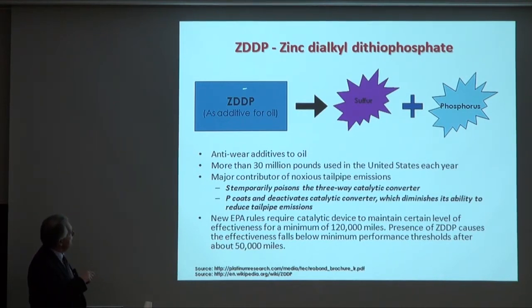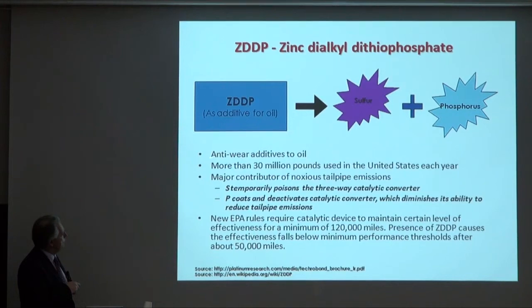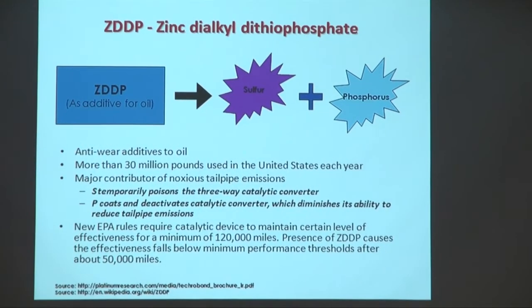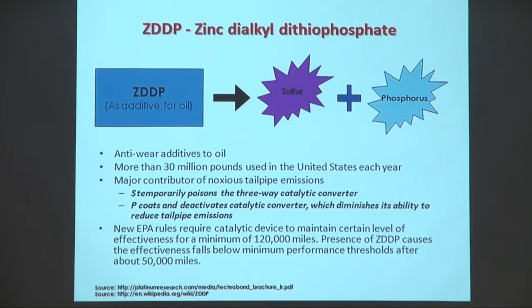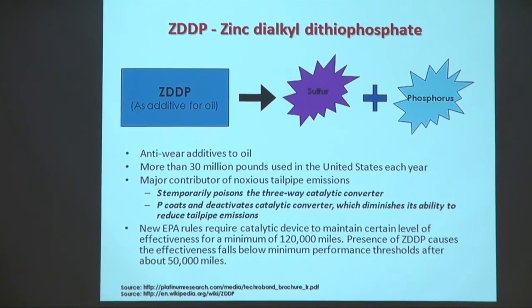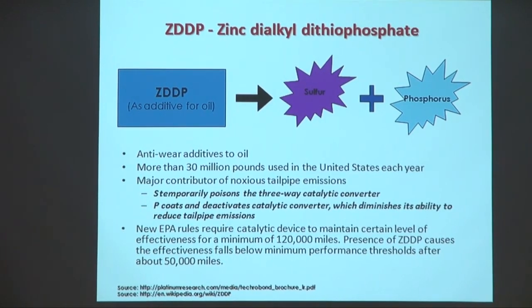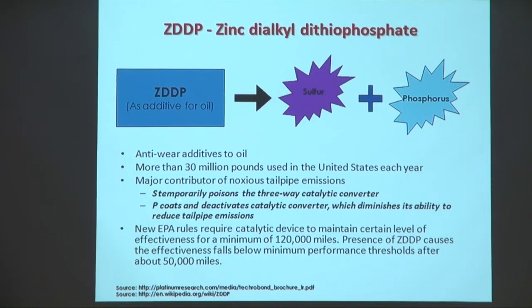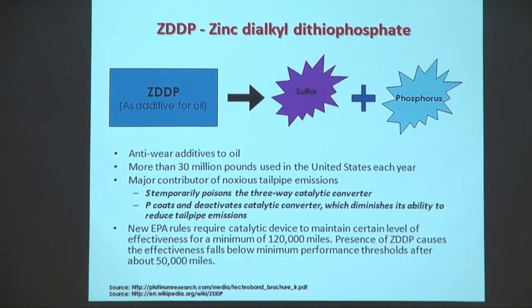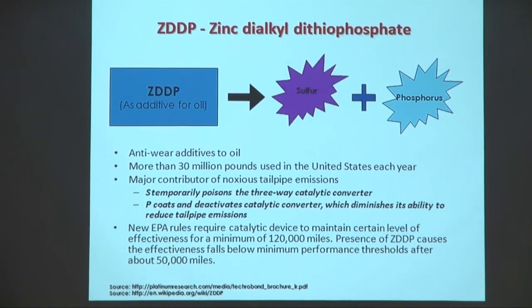So we said that zinc dialkyl dithiophosphate is one of the prime additives in the oil, but unfortunately this has sulfur and phosphorus. And although this is the anti-wear additive to oil, and we have more than 30 million pounds sold per year in the US alone, it's the major contributor to tailpipe emissions. So the sulfur temporarily poisons the catalytic converter, and the phosphorus coats and deactivates the catalytic converter. That reduces its ability to reduce tailpipe emissions and also upsets the optimum combustion cycle of the engine, causing further implications.